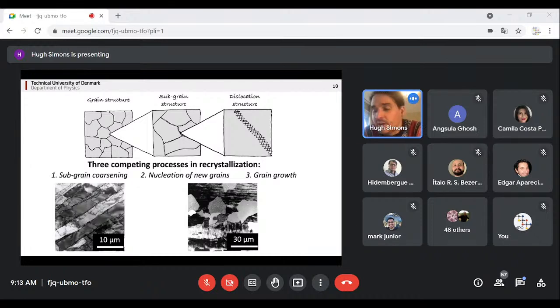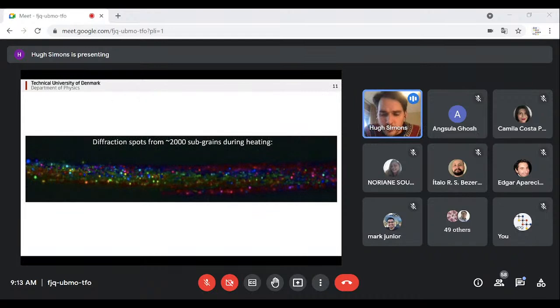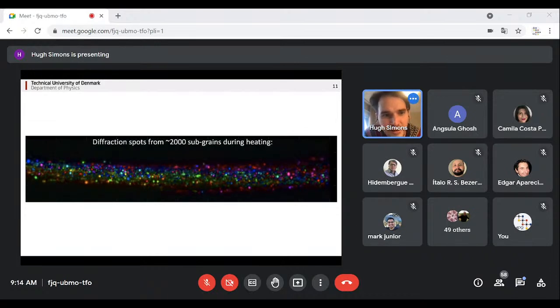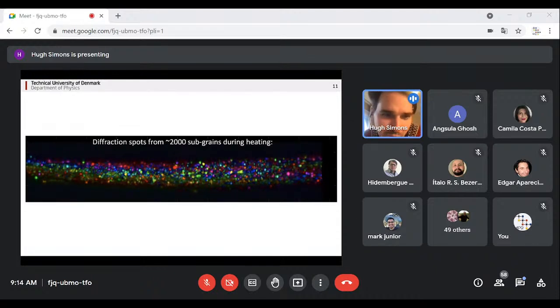So this is a nice candidate material for dark field microscopy, because the orientation resolution allows us to see these subgrain structures. This was done by a PhD student in our group, Sonia. Before she did any kind of microscopy, she started by looking at just the diffraction spots from individual subgrains. This is part of a diffraction ring, and these spots are individual subgrains. She watched them as the material started to heat up, and you can see these subgrains start to get larger and larger. It looks a bit like Christmas lights, actually.